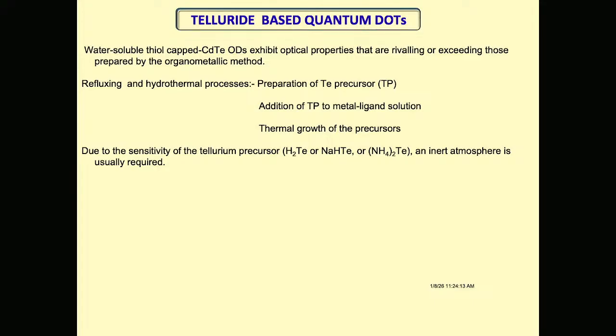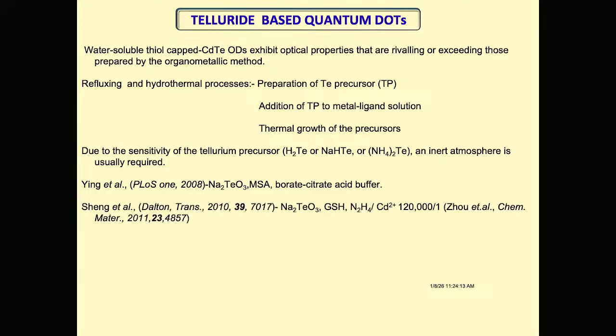And then the next material was sodium hydrogen telluride. The challenge with that is that it's not stable. The moment you prepare it, you need the presence of an inert atmosphere. Then when you begin to consider, to prepare this material, maybe you only need 0.5 mil, and then you prepare like 50 mil. So what happened to the remaining 49.5? You throw them away. So in order to solve that problem, a group in 2008 proposed the use of sodium tellurite and borate citrate acid. But there is a challenge. That citrate is also causing problems. The borate citrate is a big problem.